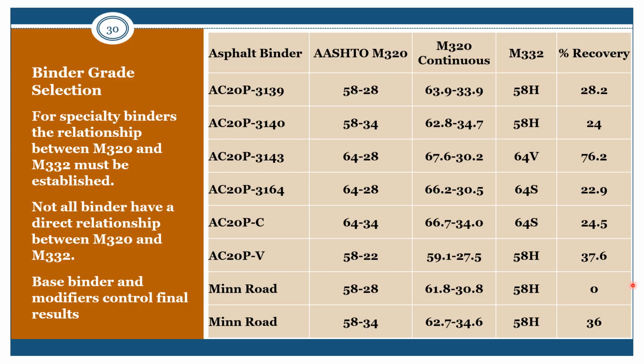So here you see several different materials: 5828, 5834, 6434. Take this 5828, this particular Mnroad material. We see that the percent recovery is 0. So even though it was a non-modified binder, at 58 degrees the J&R value said it's a little bit stiffer, it's an H grade, but there's no polymer modification. Whereas if you look at this 5828 here, this was specifically designed to be a polymer modified material. So we have the exact same, very close, within a couple of degrees, M320 specifications. But now you can see the percent recovery is significantly higher at 28.2%, even though it's still a 58H grade.